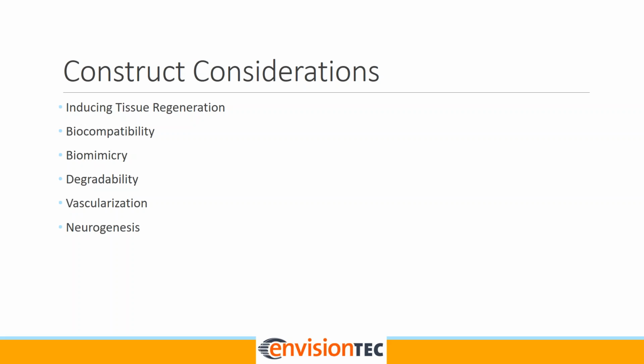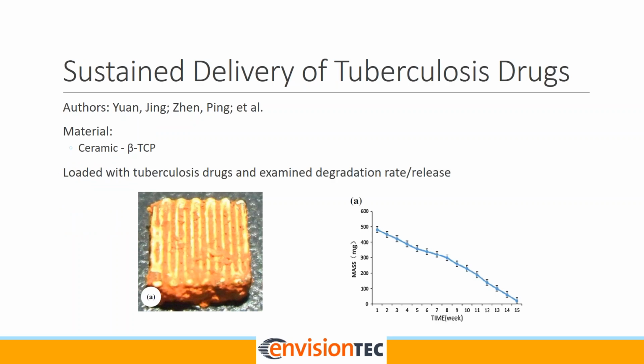So now I'd like to cover a couple of examples that'll cover the concepts that I just talked about and hopefully better illustrate these ideas. So in this particular paper, they examined the sustained delivery of tuberculosis drugs to prevent infection within a bone scaffold. So they used ceramic and beta-tricalcium phosphate as a strong bone signaling scaffold and then incorporated the tuberculosis drugs within the scaffold. And they wanted to make sure that these tuberculosis drugs were delivered at a steady rate. You wanted to make sure that the drug was always available, but you don't want too much delivered to the tissue at a time. And so you can see on the right-hand side, they were very successful in doing so.